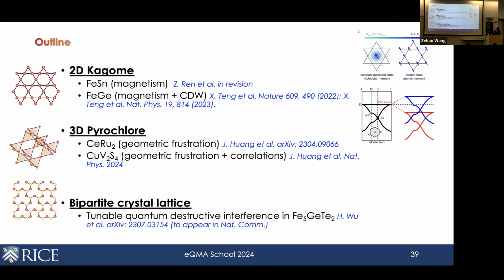Okay, so to summarize the first part, what have we done? We've looked into the Kagome lattice. First, we look at what is the origin of magnetism in this iron tin. And from that, we arrive at this local moment picture from these compact molecular states. And then second, in the case of iron germanium, we see that the effect of the splitting is to bring the Van Hove points close to the Fermi level. That alone is likely not able to drive the CDW by itself, but at least we see that in this situation, the Van Hove points are pushed to the Fermi level by the magnetic order, such as to set the stage for the eventual emergence of the CDW order.